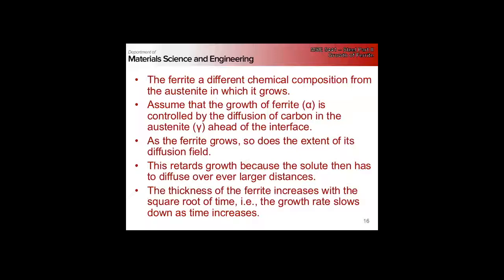We've got a partitioning, so we've got a diffusion field building up in front of our growing ferrite. The effect of this is that as our ferrite gets larger, the extent of this field gets larger, and that's going to retard the growth because our carbon has to diffuse over longer distances. Our thickness of ferrite increases as a dependency on the square root of time, meaning that the growth rate slows down.